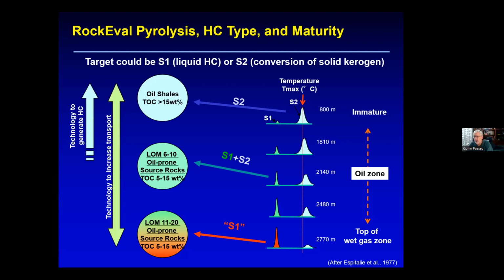It was originally developed by IFP in France at the university in Pau, but SPWLA and others have written on it. Also, Tissot and Welte, they are geochemists. I have probably a slide in another slide pack, but I'm not going to look for it. Essentially, what they will do is grind up an organic rich rock, and then put it in what's called a bomb that they can heat up. They start heating it at very low temperatures, and then they measure what's coming out of this. It's already been ground up into a powder by then, but again, it's organic rich material.